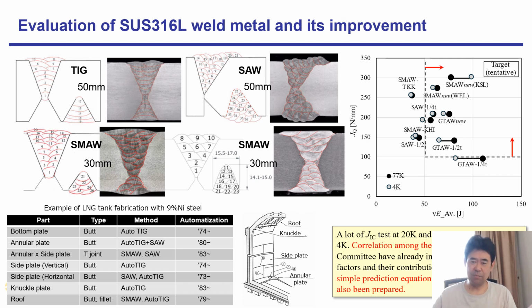However, in terms of Charpy properties on the horizontal axis, the correlation among them is not clear. So the relationship between Charpy property and J integral critical value is unclear. So the committee has already investigated the influence factors and their contributions one by one, for example martensitic transformation tendency, impurity, and delta ferrite fraction. All of these parameters are incorporated in one equation. We have established the prediction equation from Charpy 77K to JQ at 20K.